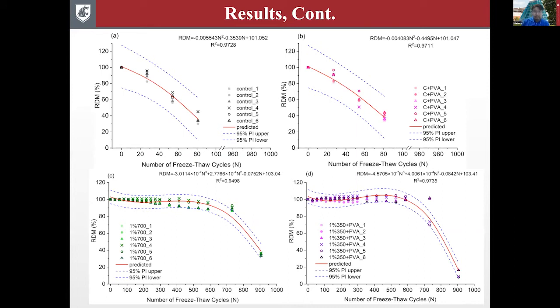Okay, here's the evolution of relative dynamic modulus of concrete specimens with respect to the number of freeze-thaw cycles. As we can see here, control specimens without the PVA fibers both approach failure after just 54 freeze-thaw cycles, while the self-healing concrete specimens can survive over 700 freeze-thaw cycles with a relative dynamic modulus of over 60%. Moreover, we can develop polynomial equations to curve fit the experimental data to predict the value of relative dynamic modulus with respect to the number of freeze-thaw cycles that a concrete specimen has been subjected to.